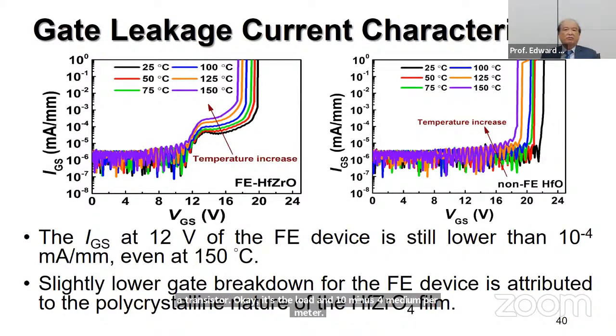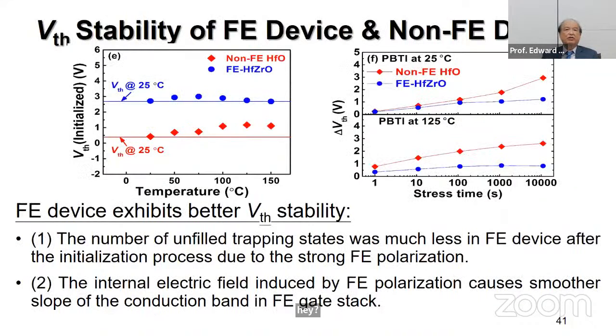And the slightly low breakdown voltage of the ferroelectric gate is attributed to the polycrystalline nature of the hafnium oxide films. And also the Vth stability of the ferroelectric and non-ferroelectric devices. The ferroelectric device exhibits better Vth stability because the number of unfilled trapping states is much less in the ferroelectric device after initialization, due to the strong ferroelectric polarization and the internal field induced by the ferroelectric, which causes a smooth slope over the conduction band in the ferroelectric gate stack.